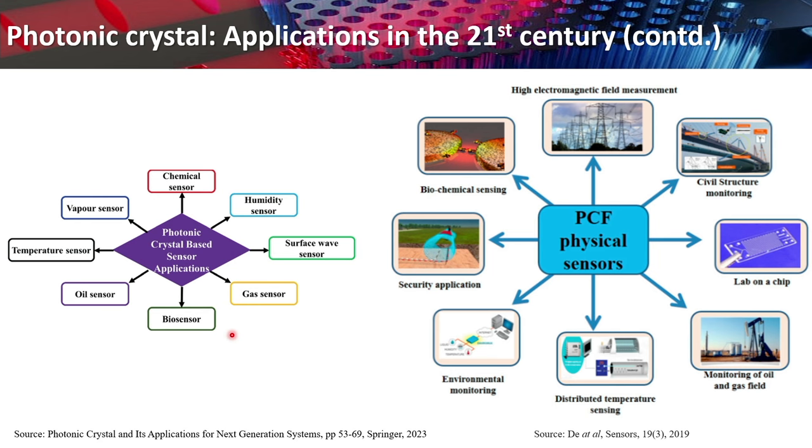So how it works, basically: the photonic crystals, 1D, 2D, and 3D, can actually regulate the flow of light through the crystal. Just like in a semiconductor, you have a semiconductor band gap. In a photonic crystal also, you can engineer the photonic band gap. So that will tell you which particular frequency of light is allowed through the crystal and which cannot enter the crystal. That will be simply reflected back. So using all these principles, you can actually develop all these different devices.